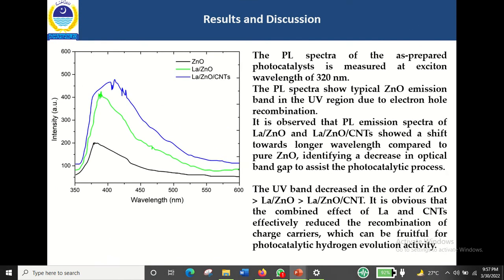So then we conducted the PL analysis, which is important to find out the wavelength of the material where it is active, and this decides its band gap energy. So the PL spectra of the as-prepared photocatalyst is measured at an excitation wavelength of 320 nanometers. These PL spectra confirm the typical ZnO emission band in the UV region due to electron-hole recombination.